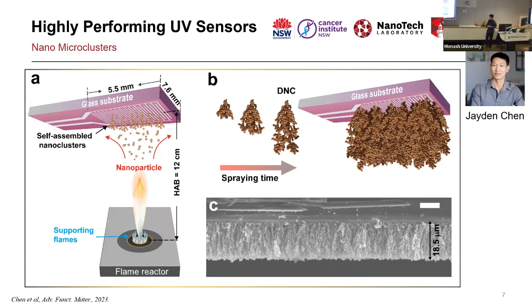So the challenge is that it is polydisperse, but you can change the particle size simply by the feeding rate. You change the feeding rate, you change the concentration, and you reduce the oxygen pressure when it's heating the droplets. If it's high pressure, the droplets are going to be significantly smaller.